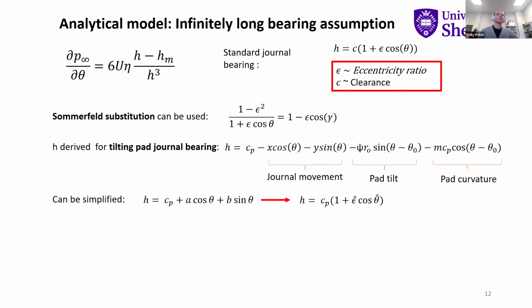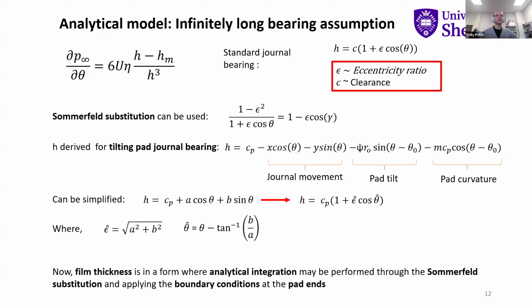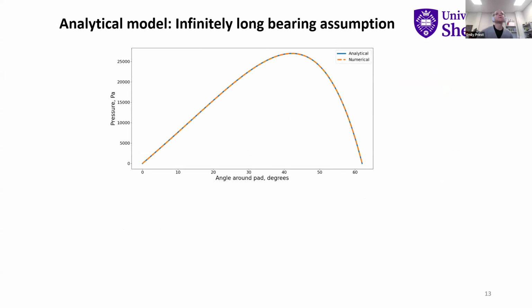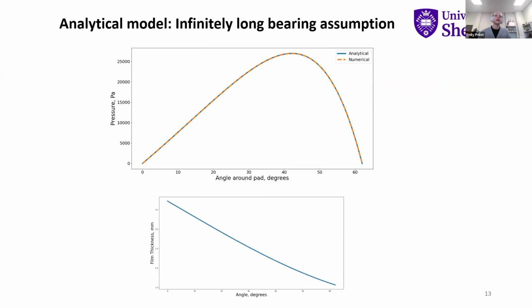So we did a bunch of maths so we could write the film thickness equation for a tilting pad journal bearing in the same way as for a standard journal bearing, and therefore we can use the Sommerfeld substitution to perform this analytical integration for the infinitely long bearing case. And when we did that, we got a pretty close match between the numerical and the analytical models. And you can see the film thickness there across the pad too.